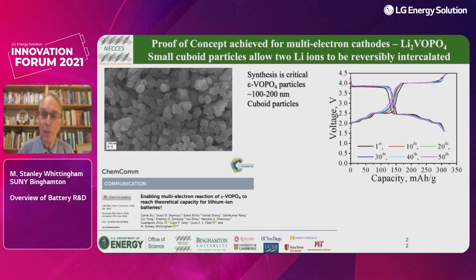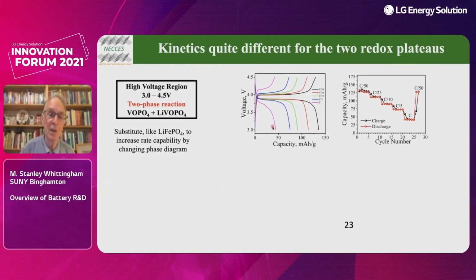It does not mean we're home and dry. We've still got lots of research to do. There are some issues here. The kinetics are quite different for the 2 redox plateaus. So in the high voltage region, we have a 2-phase reaction, vanadium phosphate and lithium vanadium phosphate. So we've got a flat discharge here. This is kinetically limited, and we're studying now how to change that.